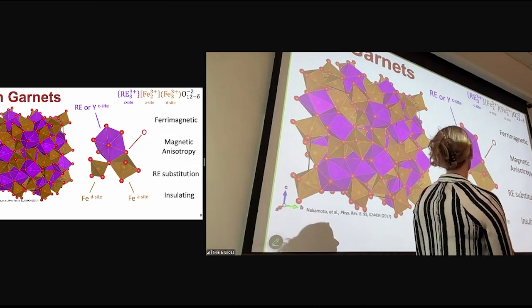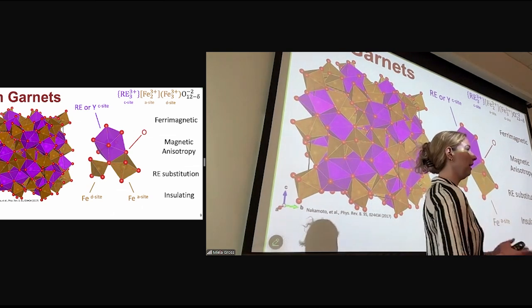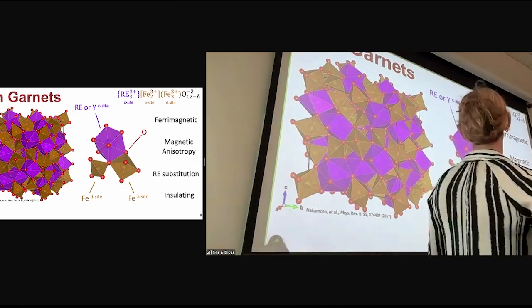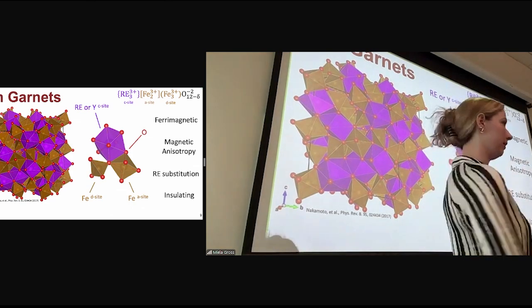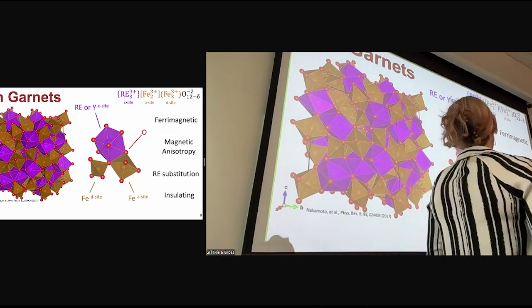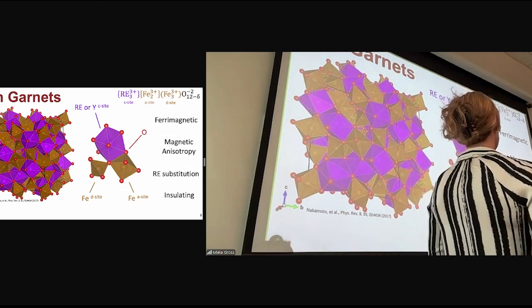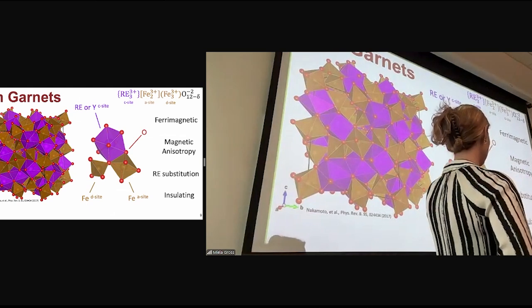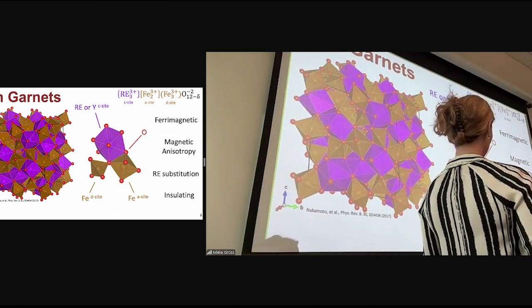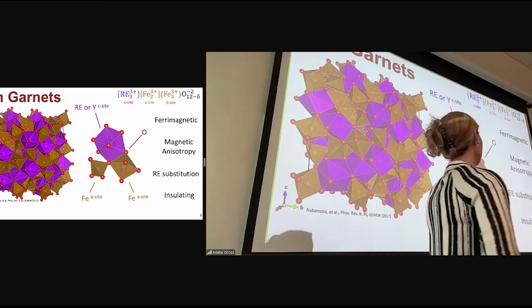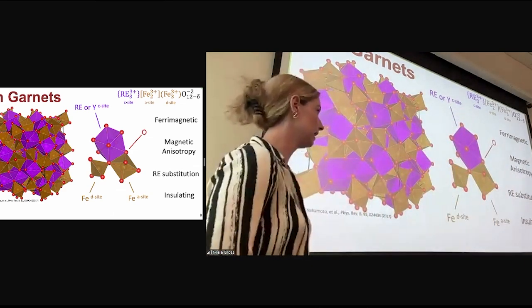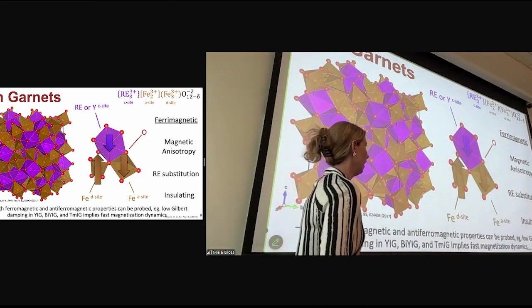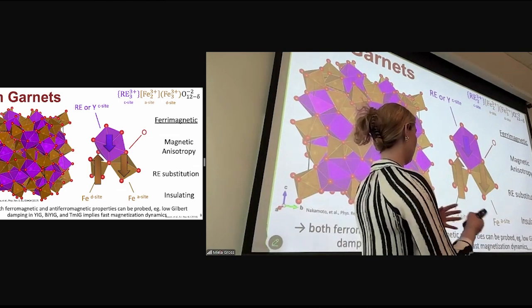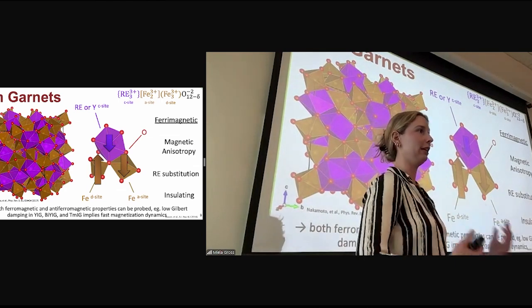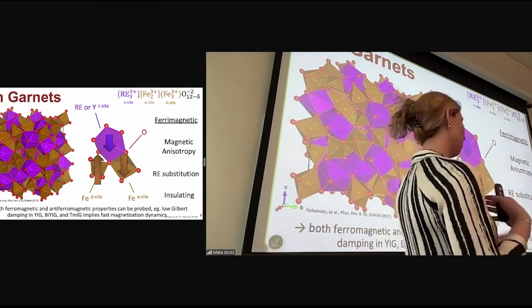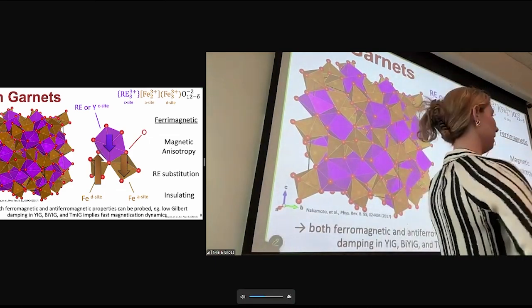So the dodecahedral site is the largest. It's also called the C site. It has the biggest atoms, which are rare earths, yttrium, bismuth, even calcium in some cases. Then the next site is this A site here. It's an octahedral site. It's where some of the ions sit. And the last site is the D site or tetrahedral site, which is where some other ions sit. And each of these sites has its own magnetic moment. And the way that those magnetic moments sum up deems this material ferrimagnetic. And that means both ferromagnetic and anti-ferromagnetic properties can be probed.